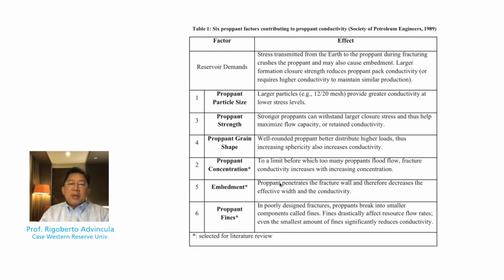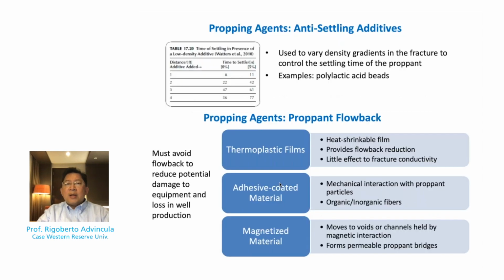Embedment, so proppants basically end up embedding on the fracture because of the high closure stresses, and therefore they can reduce conductivity simply because they become part of the fracture. And then lastly, proppants are broken into smaller pieces, and therefore these are called fines. The fines generated are much smaller particle sizes, and they can block the flow or fractures on productive zones. So all of these really are factors that may contribute eventually to low productivity in a well.